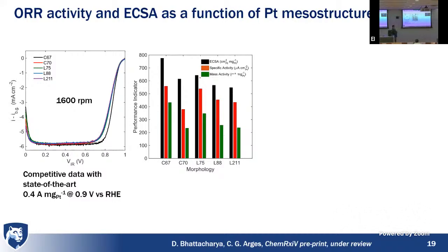This is a linear sweep voltammogram run in my lab with a rotating disc electrode setup. We analyze the current density we get at 0.9 volts, and we then normalize that to the platinum loading. We looked at several different morphologies. The C here stands for cylinder. This first one is perpendicular cylinder. This is a perforated structure, where we have holes and we put platinum. And then we have these lamella structures with different line widths.